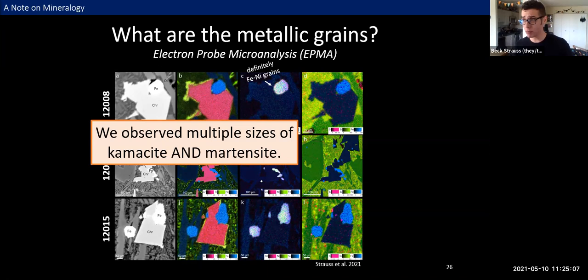which is pretty cool. Now, we were also looking at some previous studies that suggested association with troilite, which is an iron sulfide mineral, might be an indicator of paleomagnetic fidelity in lunar basalts. So we went looking for it per this fourth column, where now we have sulfur in pink, and iron in blue. And we didn't find any grains with compositions consistent with troilite. So it seems that in general, troilite may form through processes that also produce the kind of submicron iron grains that we're interested in, but it's definitely not a requirement for high paleo-intensity fidelity.